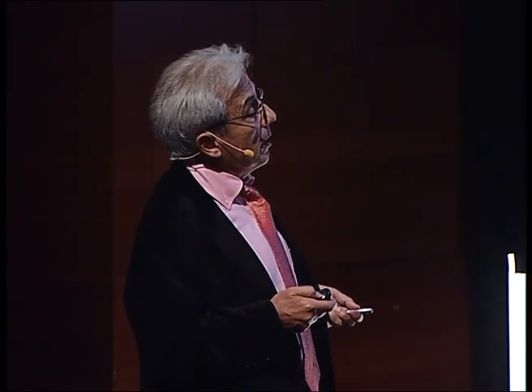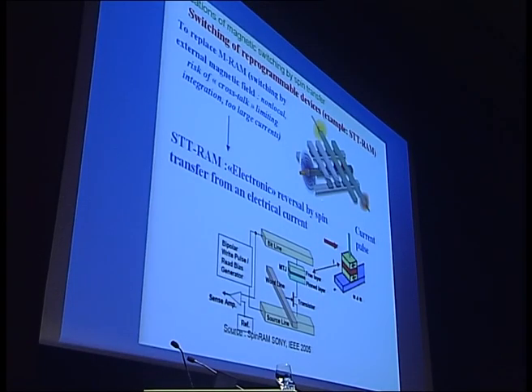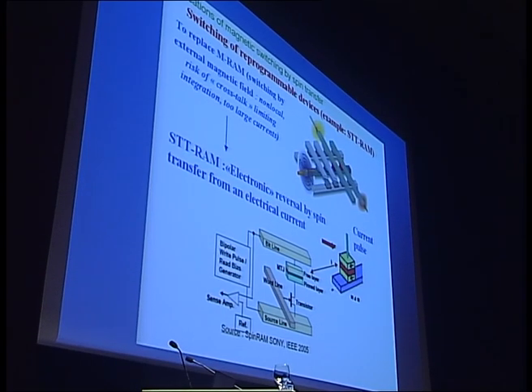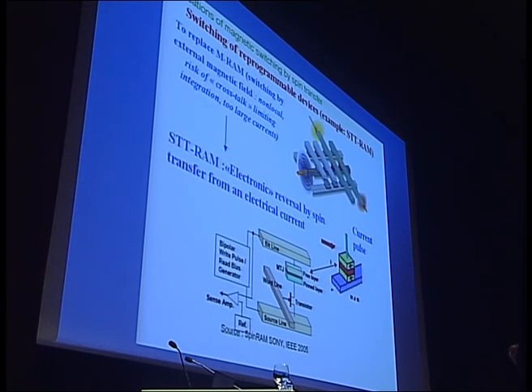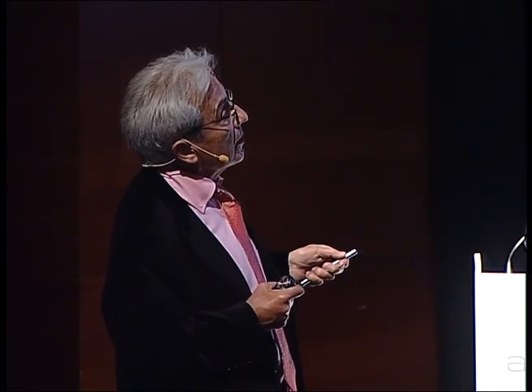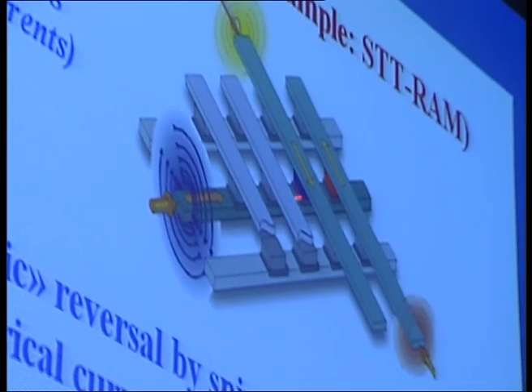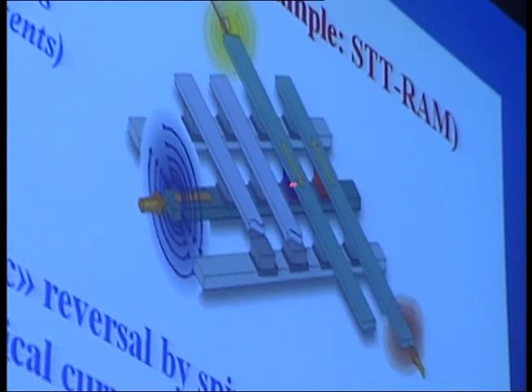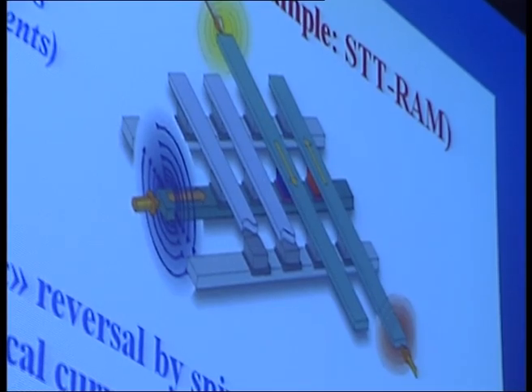Application of this switching by spin transfer. In the first generation of MRAM, already on the market, the switching of the magnetization of one of the electrodes of the magnetic tunnel junction, the memory cells here, was obtained by current pulses in these lines, generating magnetic fields, so that the combination of the two magnetic fields was able to switch the magnetization of one of the electrodes. But this is not a very local addressing of the memory cells. There are risks of crosstalk, there is a limitation to the distance between the cells, and this is one of the limitations of the first generation of MRAMs.